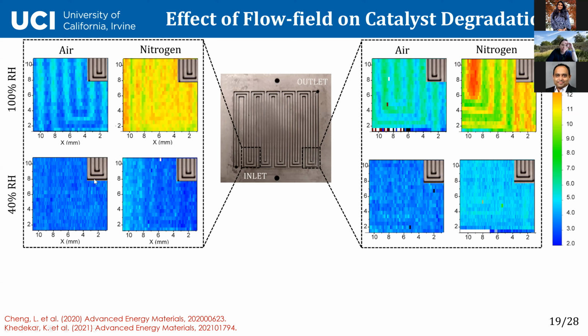Why? Because think about platinum ions. For them to move around, they need water. They need ionic conductivity, right? So ionomers provide that, but ionomer ionic conductivity is proportional to relative humidity. So when we have 100% relative humidity, the ionomer is well hydrated, you have a lot of water, so platinum moves around. And what you see here is that under the lands, this is a graphite land, you see platinum particle increase, specifically in nitrogen environment, and it can go from 3 nanometers to 14 nanometers. This is really large platinum particle size.